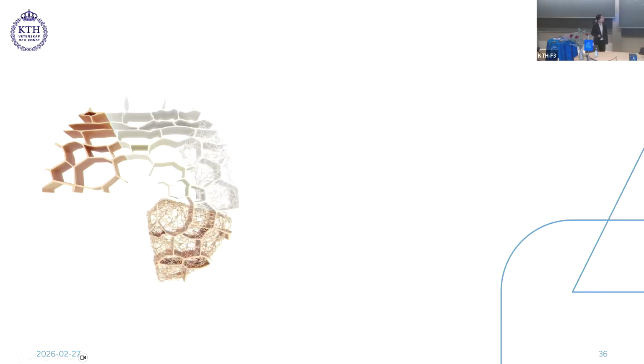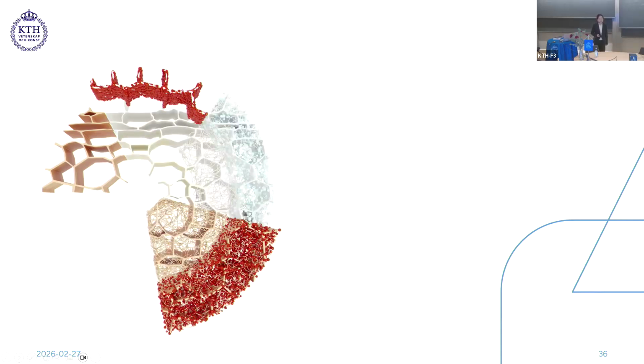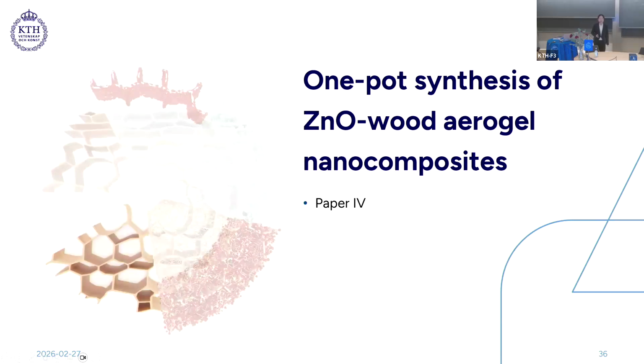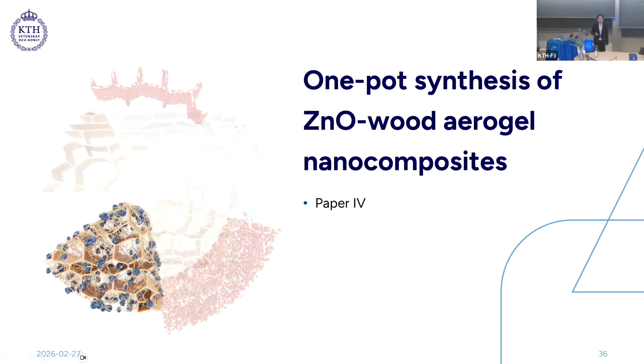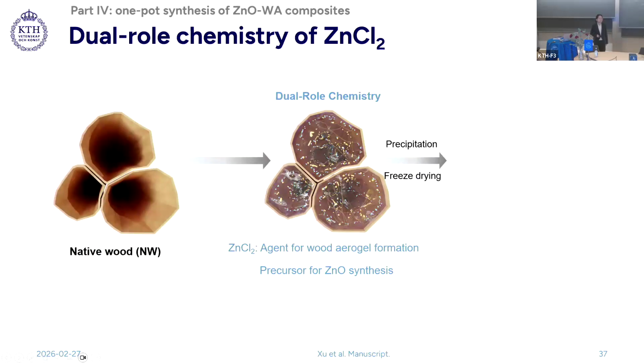From paper 1 to paper 3, the wood-based functional composite fabrication usually involves sequential steps, which are cell wall nanoengineering and functional particle deposition. In part 4, a one-pot approach was developed to combine both steps. This approach is able to simultaneously enhance the accessibility of wood and in situ synthesize the functional particles. This is achieved by the dual chemistry of zinc chloride, which serves both as an agent for wood aerogel formation and a precursor for zinc oxide synthesis.